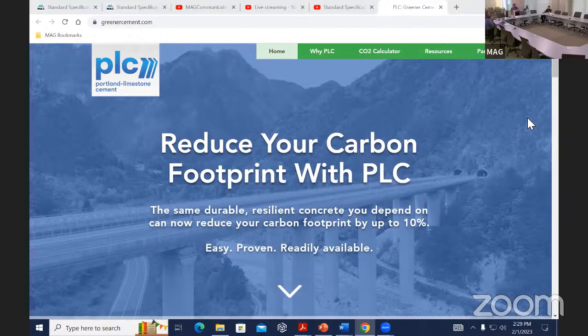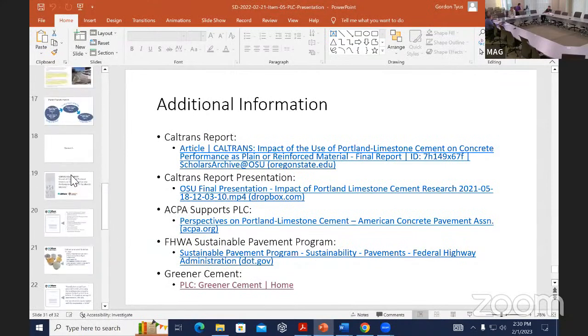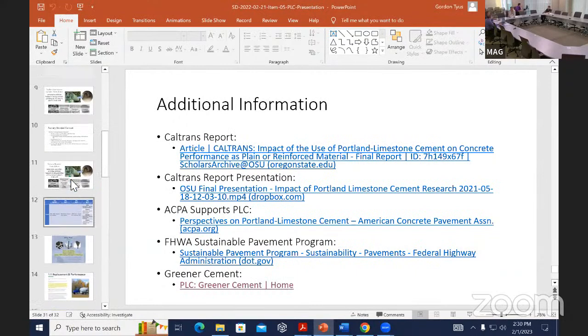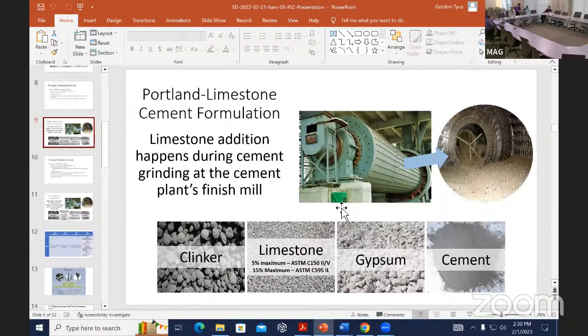My next question is, I saw that the maximum on the Type 1L in particular, you indicated the maximum limestone content was 15%. Clearly 15% was established for a reason. I'm assuming degradation of performance above 15%. If going from 5% to 15% seems to have no negative impacts, what happens after 15% that the performance is no longer found to be acceptable? There's a graph that's used quite often, and it shows X and Y axis, and it shows the limestone addition, and it takes it out for compressive strength. And the other one is, I believe, a 1202 Coulomb rating for porosity, for ingress.